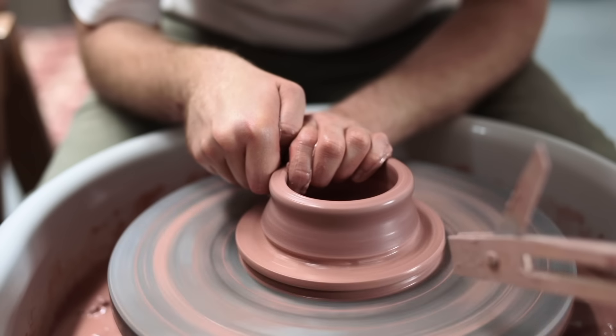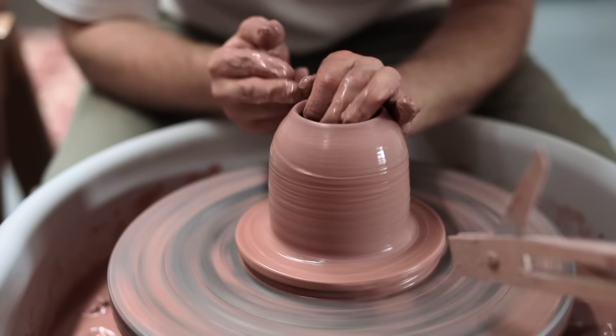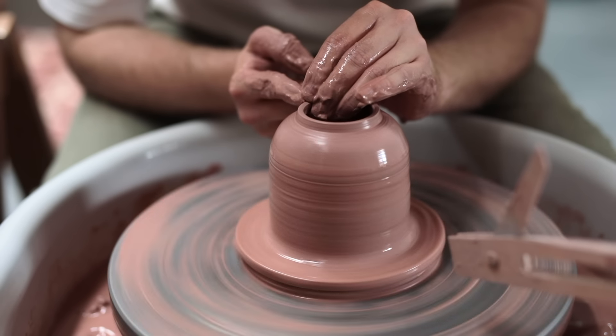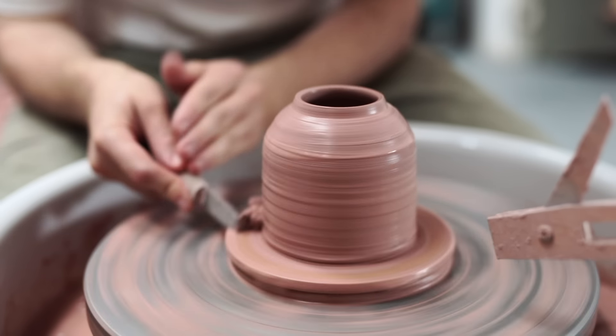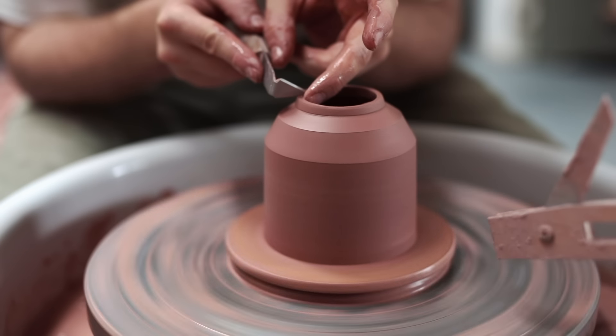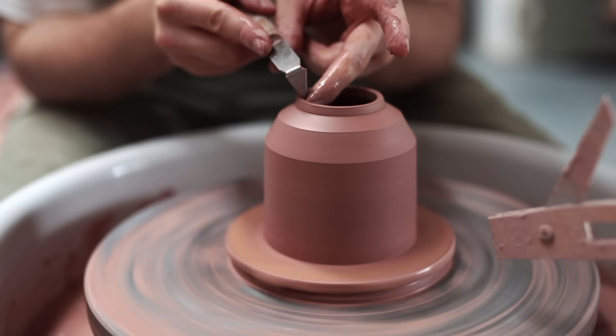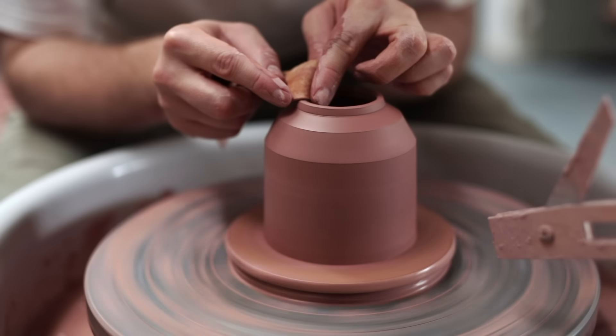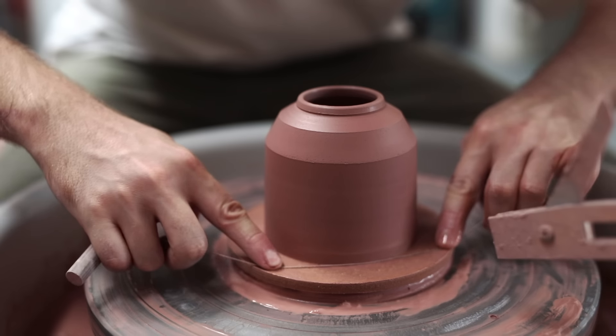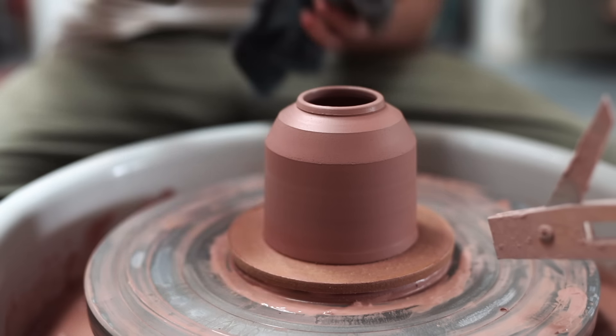The thicker ring of clay around the outside is then pinched and pulled up — not all in one go, but in a number of pulls — and I'm purposefully leaving the upper portion of the wall relatively thick, as I need enough material to collar in and throw the rim with. The lidded forms I make don't have the typical dropped-in gallery you might expect on most teapots; instead I throw a small raised gallery, and it's into this opening the lid slots. With the rough form made, I'll begin tidying up the shape — scraping away the slip, throwing the more exacting angles in the shoulder, and as the rim was wavering rather a lot, I sliced the undulation away using the sharp edge of a turning tool. I then chamois leather the lip smooth and measure the width of the opening using calipers before wiring the pot off the bat.